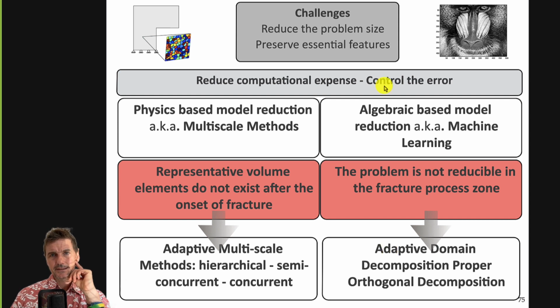And this is what the slides mean. So you have, in the physics-based approach, a representative volume element that does not exist after the onset of fracture. And in the case of algebraic-based model reduction, the problem is not reducible in the fracture process zone, so close to the cracks. So this is why in both cases, you will have adaptive domain decomposition and adaptive multiscale methods. And so this is basically what you should know about this.